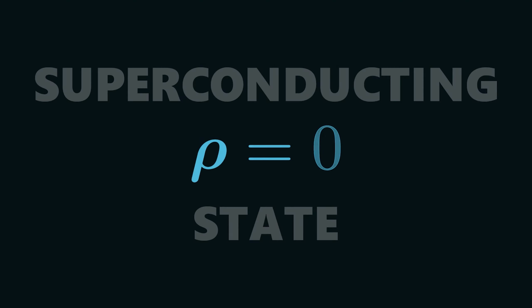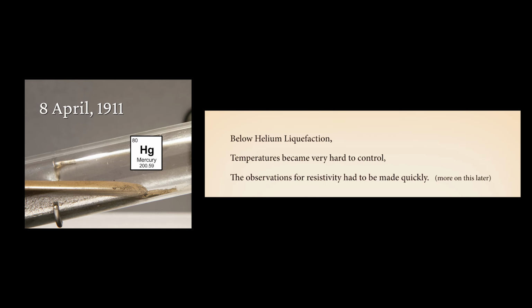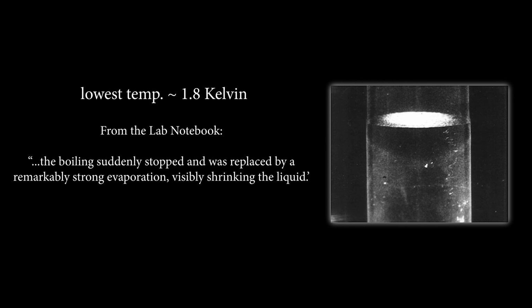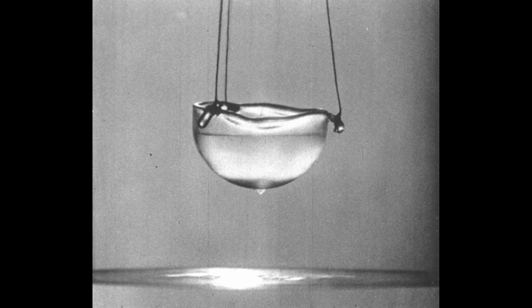Superconductivity is the phenomenon where the resistivity of a material drops to zero below a particular temperature. But remember how in April 1911 it had become very hard to control the temperature of liquid helium, and we know this from the entries in the lab notebook. The lowest temperature reached in that experiment was 1.8 Kelvin. Near this temperature, the boiling of liquid helium was suddenly replaced by remarkably strong evaporation at the surface, and the liquid visibly shrank. Without realizing it, the Leiden team had become the first humans to observe the superfluid transition of liquid helium.